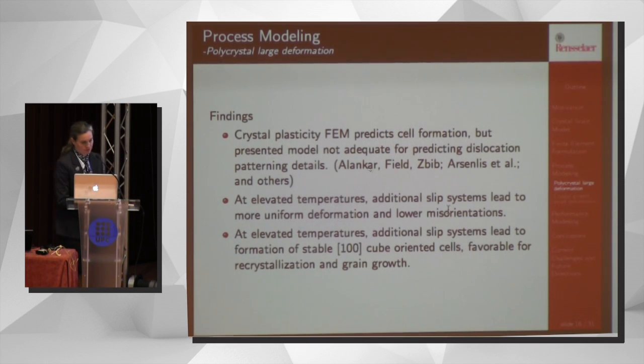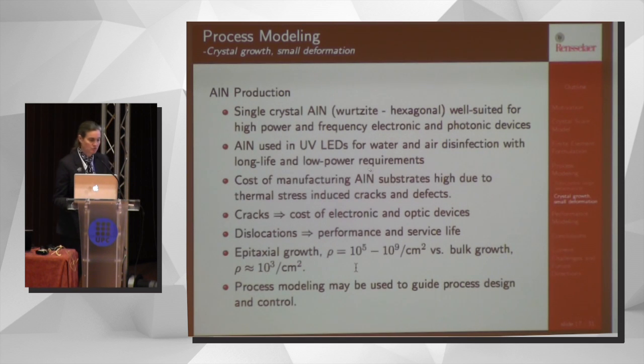The other thing we found was that at elevated temperatures, these additional slip systems lead to more uniform deformation and lower misorientations, and also the formation of this stable cube orientation that's favorable for recrystallization and grain growth. So adding those slip systems is important to predict the correct texture, and then if we wanted to link this up to some type of grain growth simulation. The next example in process modeling that I want to talk about is aluminum nitride production.